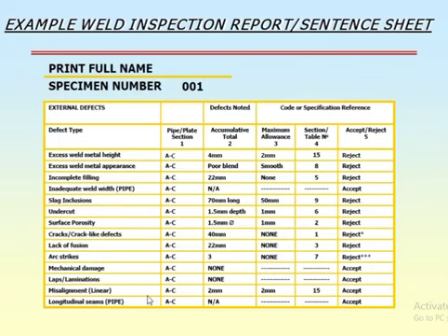Okay, and misalignment is 2 mm, the table number 15 accept. So you see here, the misalignment is 2 mm, but the maximum allowance is 2 mm, so it is accepted.